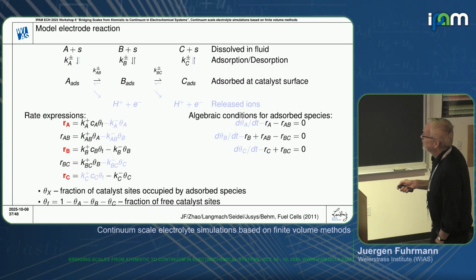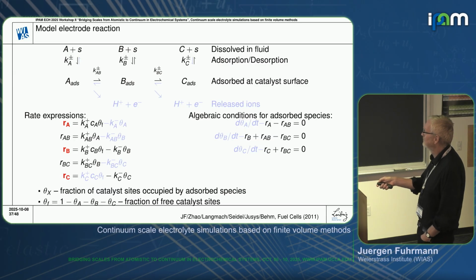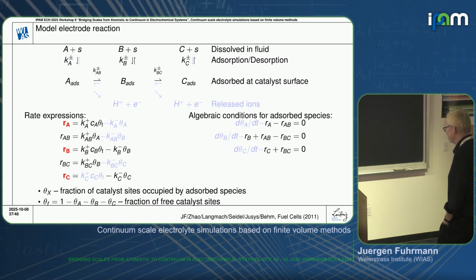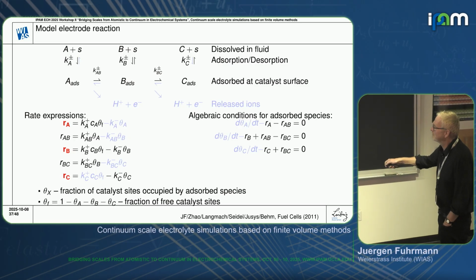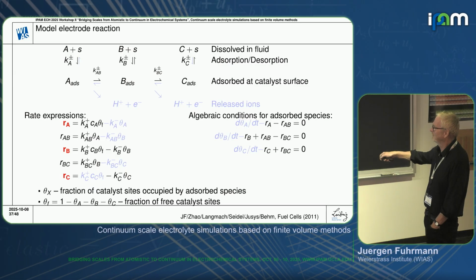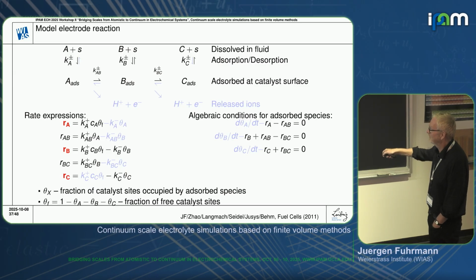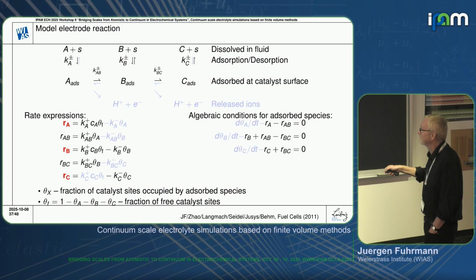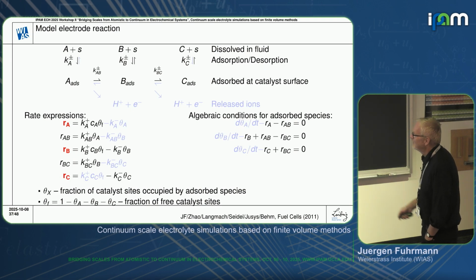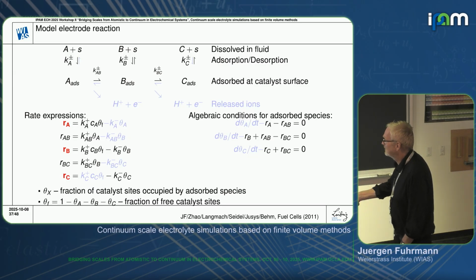And then we can model this in such a way that we have our dissolved species. They can adsorb to the catalyst surface and react on the catalyst surface from A to B to C, and of course then also desorb. And if we would have a fully electrochemical experiment, we would also just have the corresponding reaction to protons and electrons and the corresponding current, which we ignore in this case. This can be then described by rate expressions, which take into account the fraction of the free catalyst site.